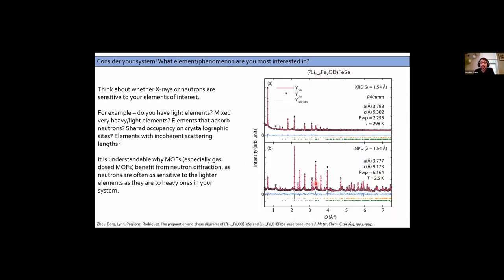Okay. And so this is an example of how these diffraction patterns change, right? This is not a MOF material, but it's a good example from the Rodriguez group, also at ORNL, where you see the differences between the patterns, right? You see the X-ray scattering pattern dies off. That's a function of the X-ray form factor, whereas the neutron pattern holds constant. And that's because the scattering length is constant over Q, right? And Q is normalizing, if you will, to the wavelengths. So you can see there's a difference, right? From the neutrons, you also get a lot of information out here at the high Q, which is your local structure, your thermal parameters. So there's a lot of advantages to using neutron diffraction in and of itself, and when you complement it with X-rays, right?